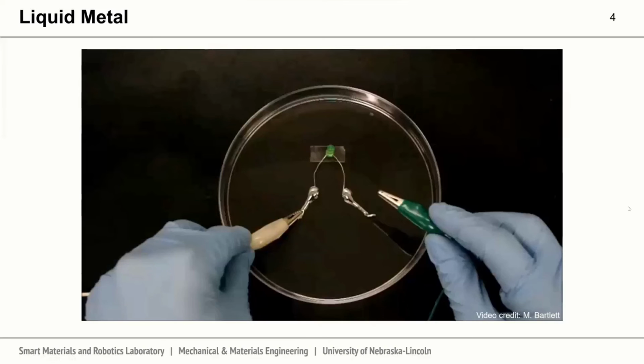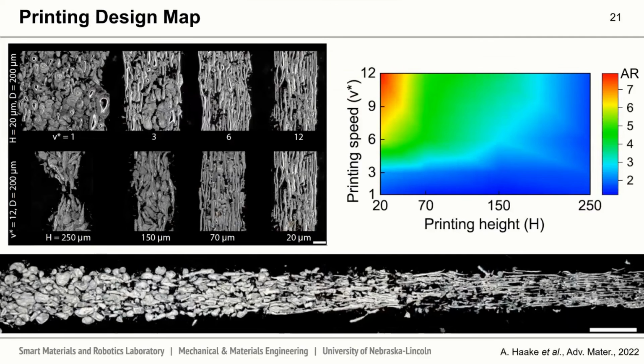Can you orient the liquid metal needles perpendicular to the print plane for enhanced thermal pads, or is it limited to the in-plane direction? That's a really good question. Currently our direct ink writing setup is primarily limited to the plane. You could potentially create a very tall, slender structure, and while that might be difficult, you could then orientate it perpendicular to the plane. There's been other research integrating ferromagnetic particles into the liquid metal, curing the composite within a magnetic field to orientate it with respect to the in-plane direction. But our direct ink writing process as is is primarily limited to in-plane.